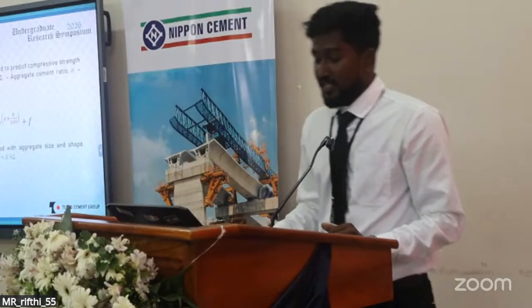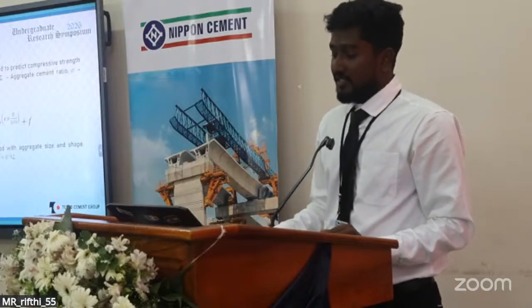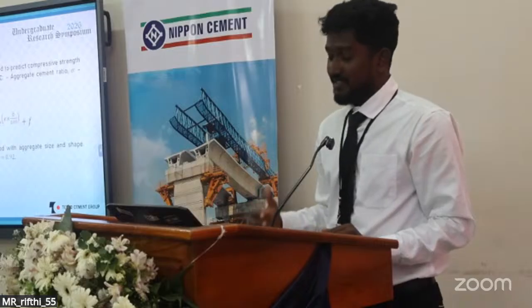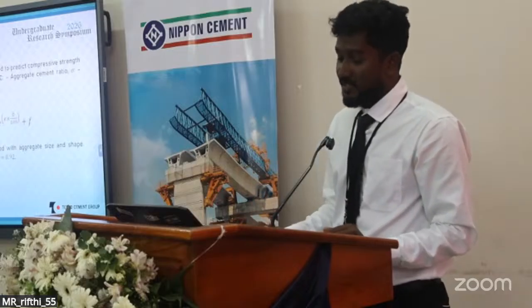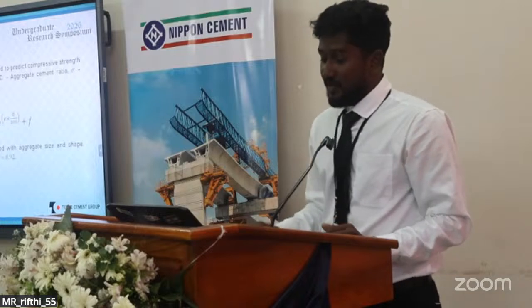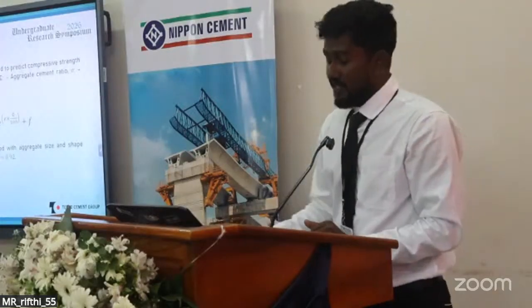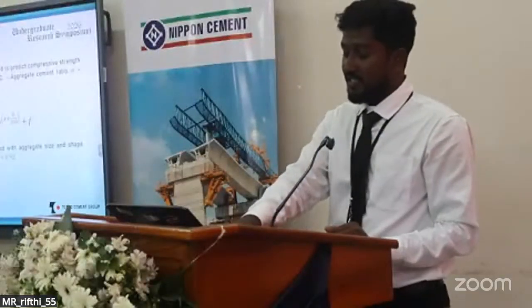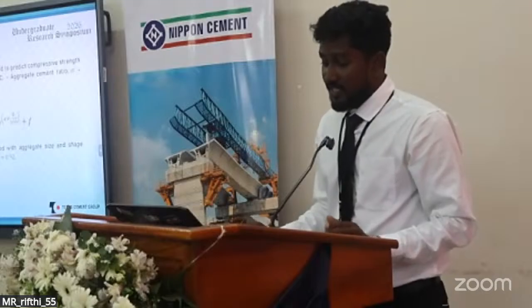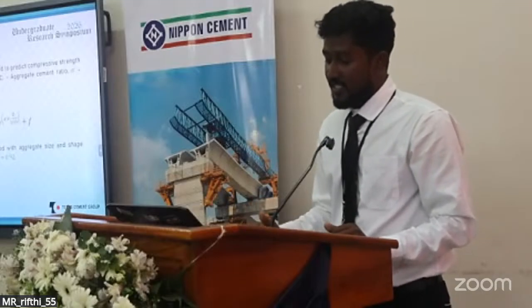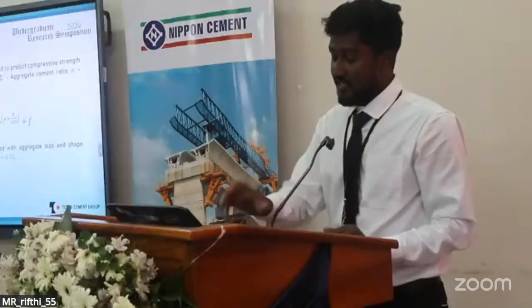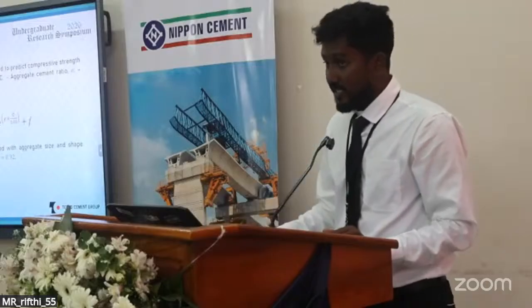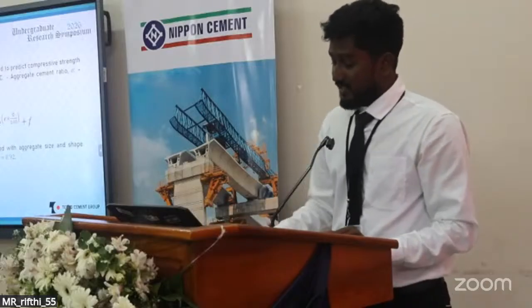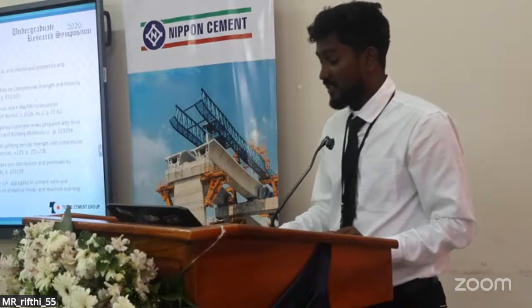From this conclusion, based on the results for the porous concrete, the porosity, compaction, aggregates, and cement ratios, all of these affect the compressive strength of porous concrete. From this equation we predict the compressive strength of porous concrete. Here B, C, D and E are without change. Here we change only A and F, which represent the aggregate size and shape of pervious concrete. These are the references I used to prepare the slides, and thank you.